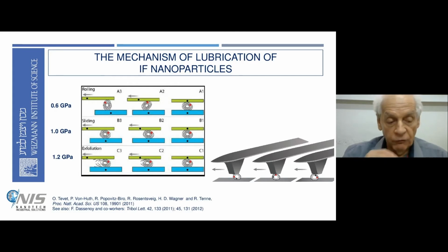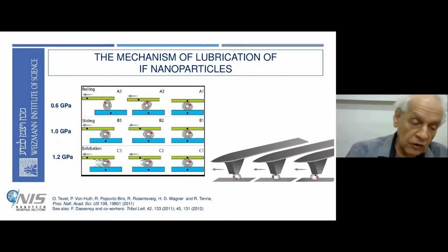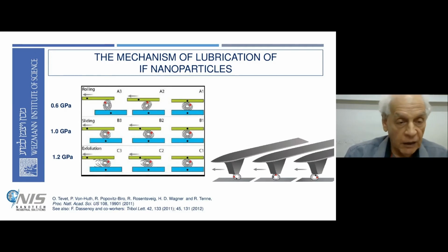So imagine, we see the rolling friction like the Egyptians saw many, many years ago, but now we see it on a single nanoparticle in a very clear fashion, and we can calculate the friction coefficient and show that this is indeed a very good and very efficient lubrication mechanism.